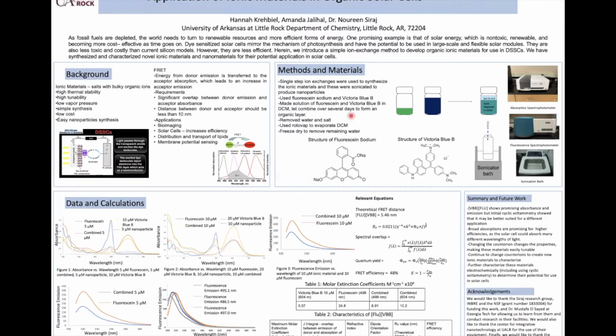There has to be significant overlap between donor emission here and acceptor absorbance, which is this J integral value. And the distance between the donor and acceptor material has to be less than 10 nanometers in order for the energy to be transferred. After we synthesized this material, we wanted to characterize it photophysically to see if it was exhibiting FRET or if it would work well in solar cells. So we characterized it using absorbance and emission.